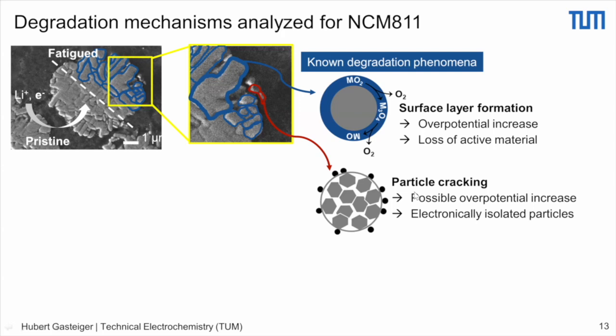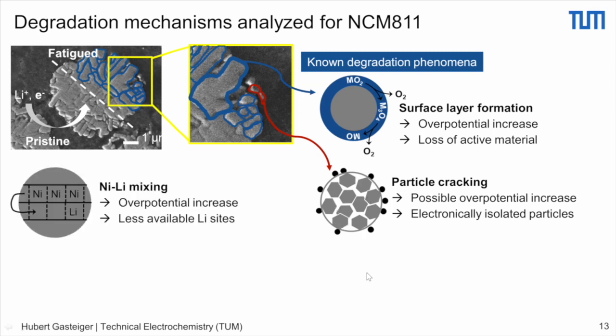The other thing is, of course, we know that we can get particle cracking, so it can become extreme, so that really single particles could be released, and then we would have a possible overpotential increase because we have electronically isolated particles in the center of the secondary agglomerates. And the third one is, of course, the nickel-lithium mixing, which in principle also should lead to an increase in the overpotential, and to a reduced availability of lithium sites for intercalation.